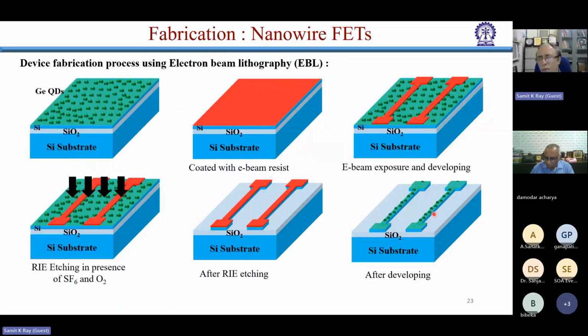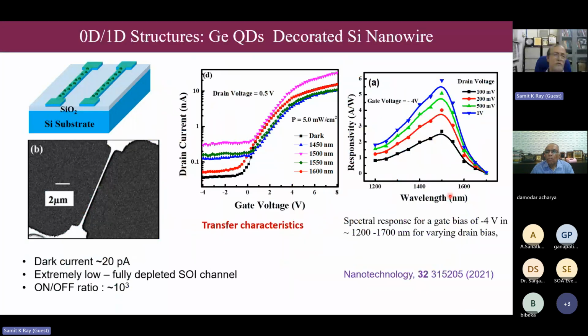Now, silicon does not actually absorb in the optical fiber communication wavelength, but germanium does. So what we can do, we can use the germanium to detect the NIR photons, and use the silicon transistor to collect them. So that's what we do. So this is the finally fabricated device. And you see that typical device dimension is in the range of about 100 nanometer or so. And we basically make field effect transistors. I don't want to go into detail of that, but this works perfectly, the current voltage characteristics of a FET. And this has got different response to different wavelength. And we get the best response because of germanium band gap around 1500 nanometer. So that is very, very close to optical fiber communication wavelength.